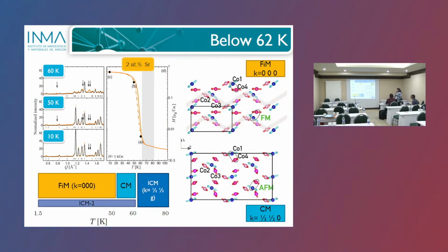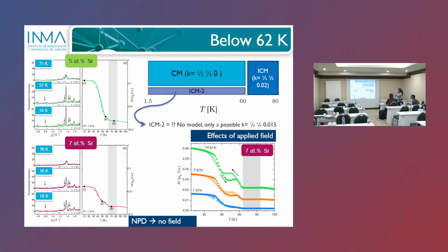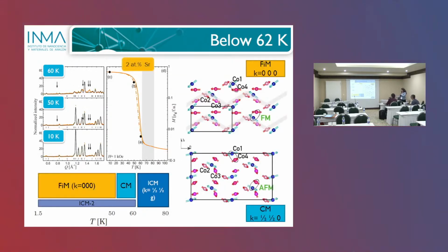Another thing that we observed, indicated with these black arrows, is very tiny additional peaks. These peaks are of magnetic origin, and they are not accounted for by any of the models that I have been discussing, neither the ferrimagnetic one nor the commensurate antiferromagnetic one. And so we call this a second additional incommensurate phase, because if you try to index the position of these peaks, they are compatible with a propagation vector that is also incommensurate.